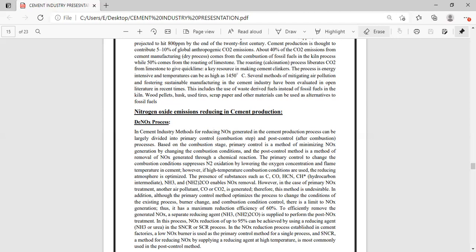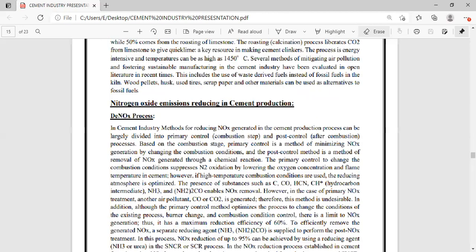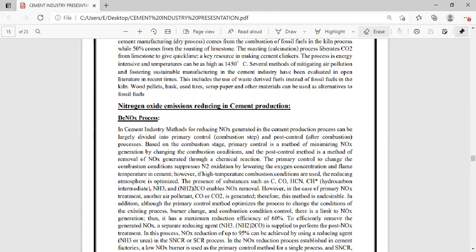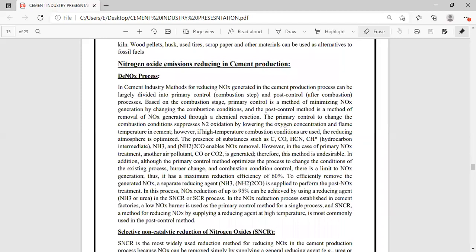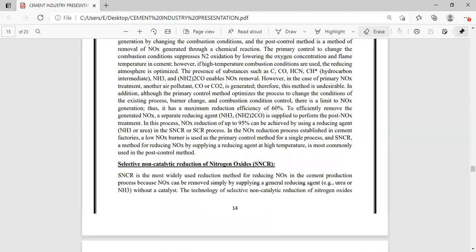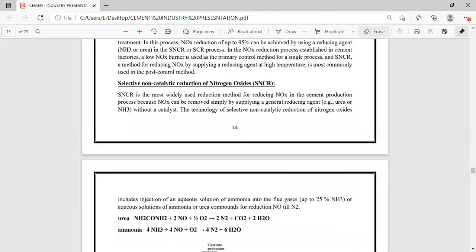In the case of primary nitrogen oxide treatment, another air pollutant, carbon monoxide or carbon dioxide, is generated. Therefore, this method is undesirable. In addition, although the primary control method optimizes the process by changing the conditions of the existing process, there is a limit to nitrogen oxide generation, thus it has a maximum reduction efficiency of 60%. So the first method for nitrogen oxide removal: selective non-catalytic reduction of nitrogen oxide.